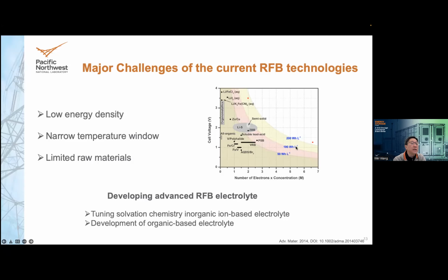And the lower end lithium-ion battery is this outer line of 200 watt-hour per liter that are based on the lithium iron phosphate with graphite anode. So one major issue in the redox flow battery is to increase the energy density by increasing the concentration of the electrolyte and also increasing the temperature window. And those two are often related. The temperature stability is often related with its concentration in the particular temperature range.